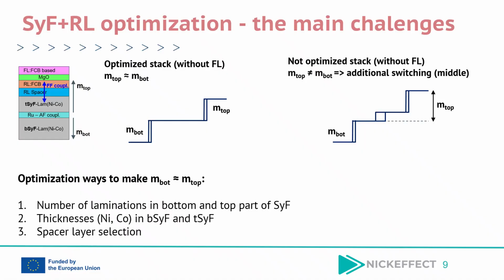In the non-compensated SyF structure, imbalance between the magnetic moments of the 2 SyF parts may destabilize the coupled switching behavior, leading to the appearance of intermediate switching states in the hysteresis loop. This results in a reduction of the operating window and degradation of the switching characteristics, significantly limiting the application potential of the MTJ structure. As illustrated in the schematic, the magnetic moment compensation can be achieved by adjusting the thickness or the number of cobalt-nickel multilayer repetitions in the top and bottom parts of the SyF structure.